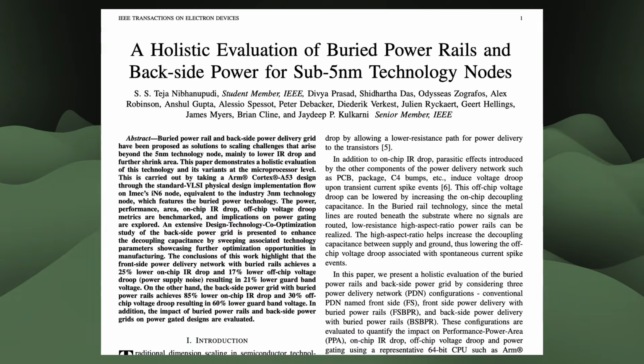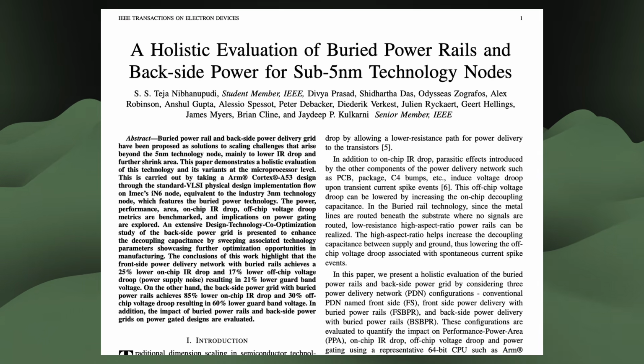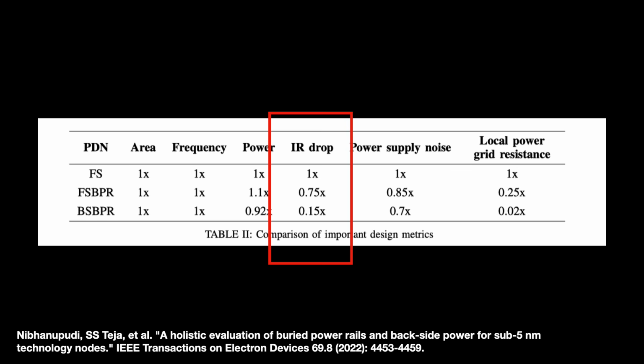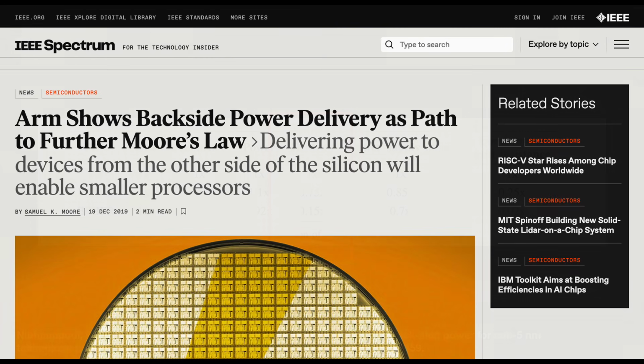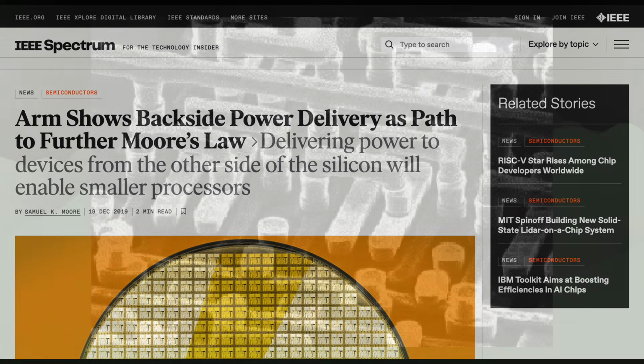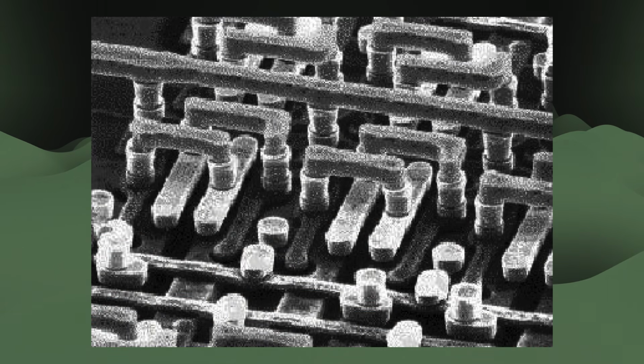How much? A study at the University of Texas, Austin, found that power consumption is about 8% better with BSBPR over a standard frontside power delivery network. More critically, IR drop is significantly reduced to about 15% of that from the frontside configuration. ARM presented simulation results back in 2019 showing something similar, a 7x improvement. There are knock-on benefits too. Moving out the power interconnects lets us spread out the signaling interconnects on the top side. More space cuts down on their parasitic capacitance, unwanted stored charge that hinders their signaling speed.